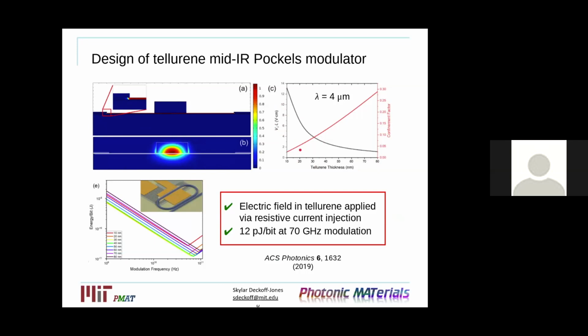So another figure of merit for modulators is often the energy per bit. So you want to be able to encode information at very low energy costs. And as we increase the thickness of our tellurene, we also see a larger resistive power consumption. And so by going to thinner thicknesses, we have less energy at the expense of weaker modulation. So again, there's this interesting trade-off between the modulation efficiency and the energy and its thickness.